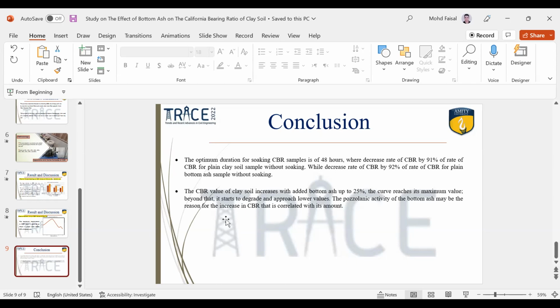No, I didn't check the required density. I got the OMC for each composition by the Proctor test. Then we mixed the bottom ash with the clay soil. So as per your finding, CBR increases with bottom ash up to 25%. Yeah, this is the optimum content. So what was the increase in the numbers? What was the CBR value before and after?